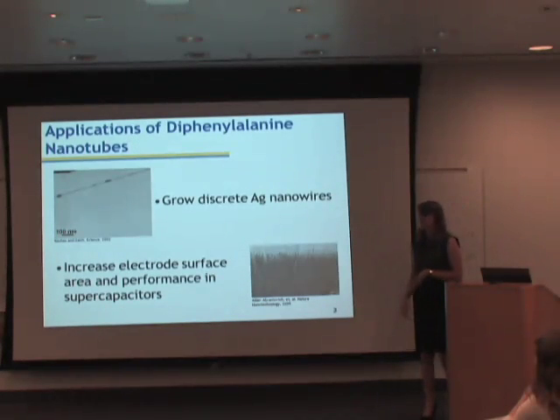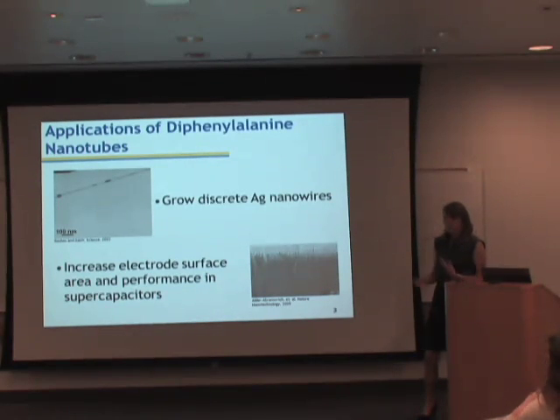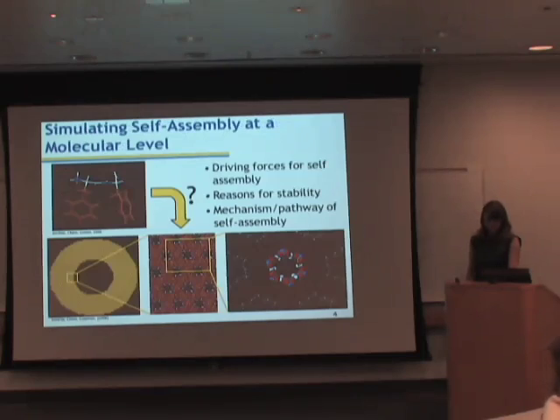And diphenylalanine nanotubes have many applications outside of the biological field. For example, silver nanowires can be grown on the inside of these nanotubes, and the nanotubes can subsequently be degraded away using enzymes, leaving a discrete silver nanowire. Diphenylalanine nanotube forests can also be grown on a surface using a vapor deposition technique. In this way, we can increase the electrode surface area and thus the performance in supercapacitor devices, which are potentially the future in energy storage.